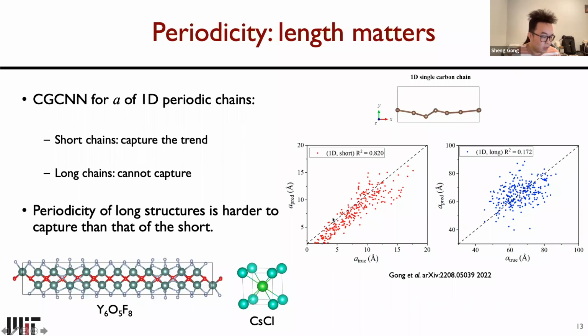In the figure on the left, we show the predicted lattice constant and the true lattice constant of these one-dimensional chains with short periodicity, where we can see that CGCNN can actually capture the trend, although not perfectly. The trend is clear. And on the right, we show the predicted periodicity and the true periodicity for these long chains. We can see that for the long chains, the trend is not clearly captured, which agrees with our previous analysis that the periodicity of long structures is harder to capture than that of short structures.